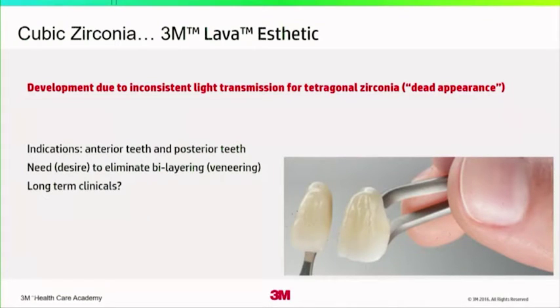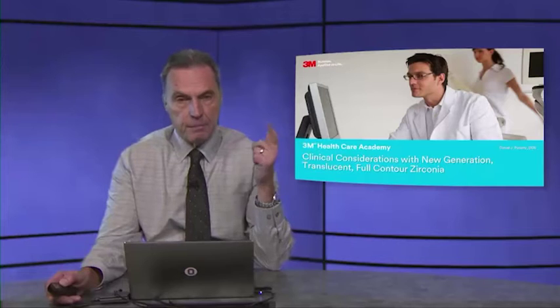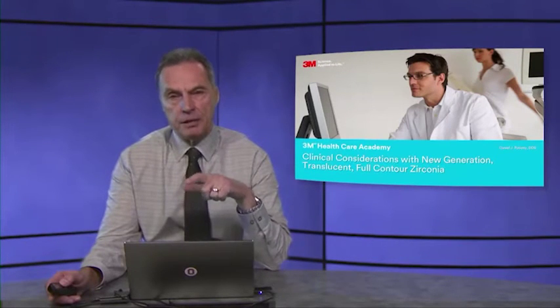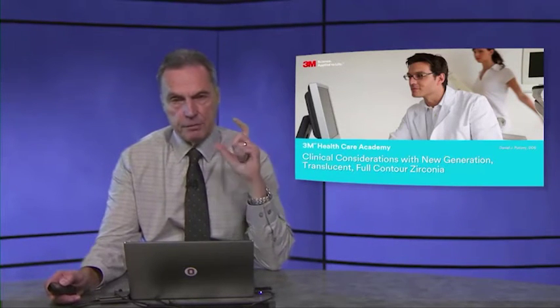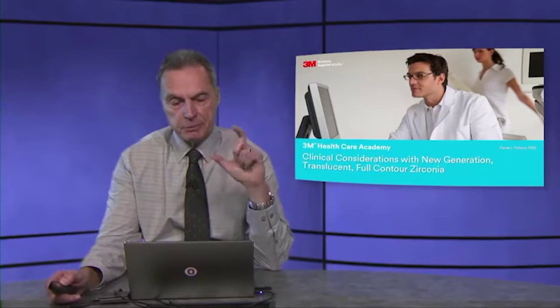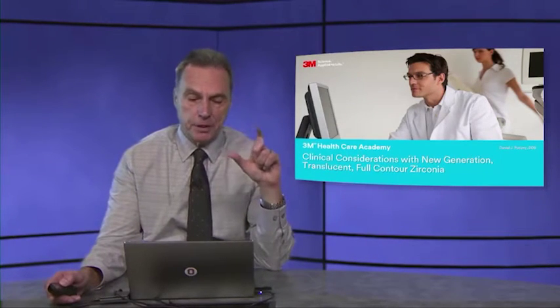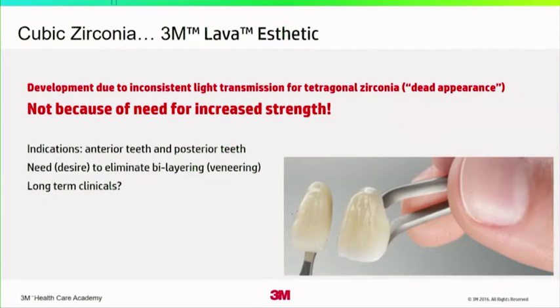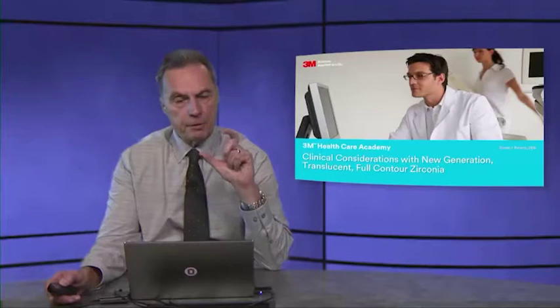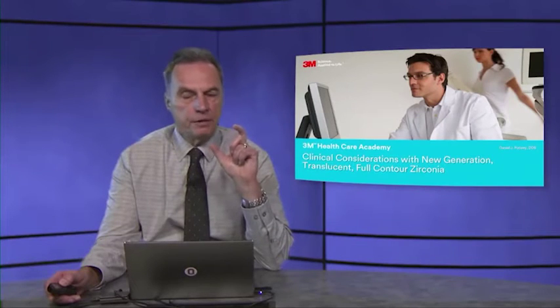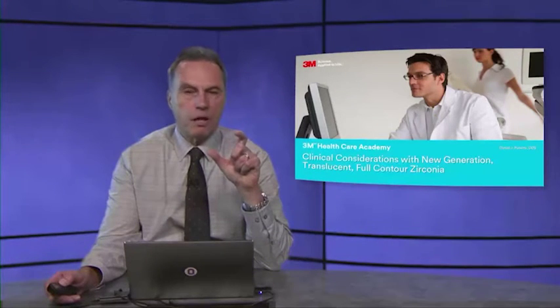Vitality, as you know, is associated more with the fluorescence and to an equal amount with the transparency of the material itself. But what you need to keep in mind here, and we'll have a little discussion about this, is that this material was developed to meet that specific need. It is not developed, however, for the need for increased strength. Because the truth is, properly handled, whether you're using a glass ceramic or a crystalline ceramic like zirconia, with proper technique, we've had high survivability for all of these materials.